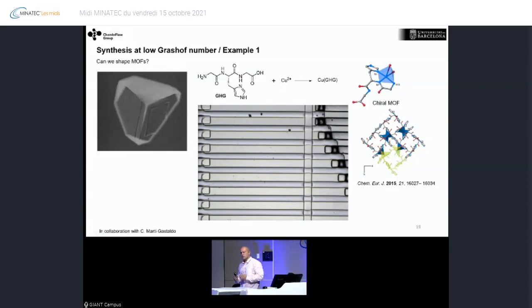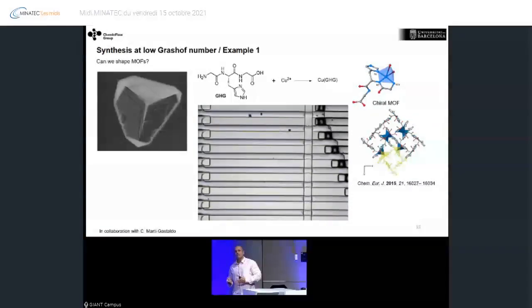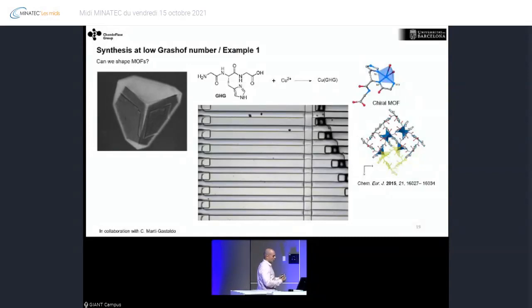So then the question here is, if we have this free interface diffusion process, can we use this, for instance, for shaping crystals? As you know, this is a MOF crystal. In that case, we cannot control how to grow the crystal. The growth is given by the crystallographic information that the crystal has. So the faces with the higher surface energy will be the faces that grow faster, right? And we cannot change that.